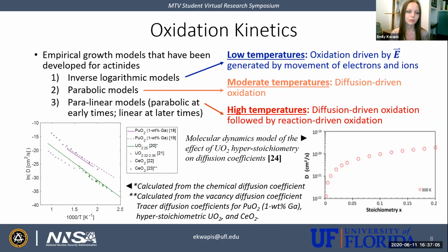In literature, there's many empirical growth models that have been developed, but the general consensus is that inverse logarithmic growth models can be used to describe oxidation at low temperatures, such as room temperature, while parabolic models are used at higher temperatures and paralinear models are used at higher temperatures yet. Diffusion coefficients, such as the diffusion of the ionic oxygen through the oxide film, does play a role in certain growth models for oxidation. So I've gone ahead and taken diffusion coefficients from literature to use to produce my models and determine the oxide film thickness as a function of time, which I will show you on the next couple pages.